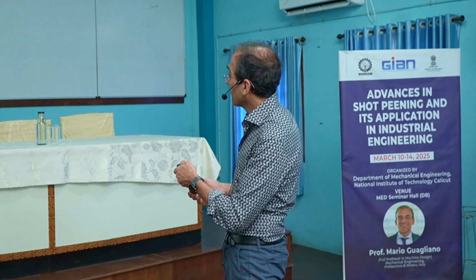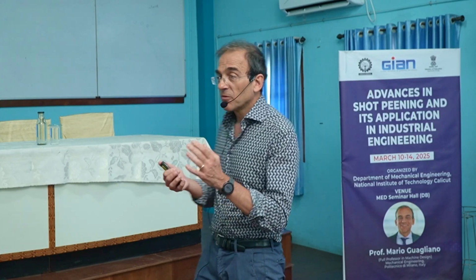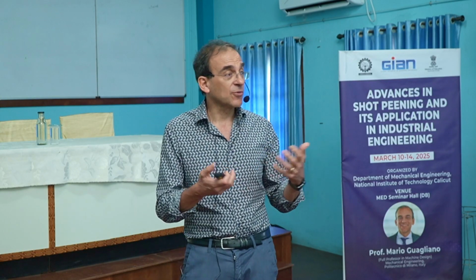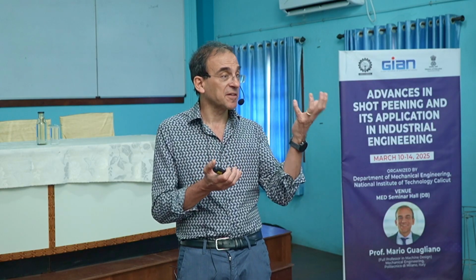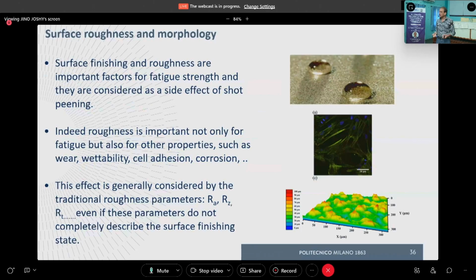Here you see these two drops on a hydrophobic surface, because the drop is retained, it's not spread along the surface, it's retained. And indeed, in this kind of surface, the roughness plays an important role. If we are able to use shot peening to get controlled values of roughness, we can use this for improving wettability. Or the same for cell adhesion.